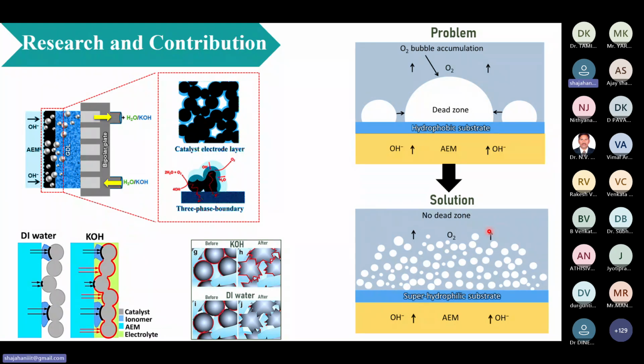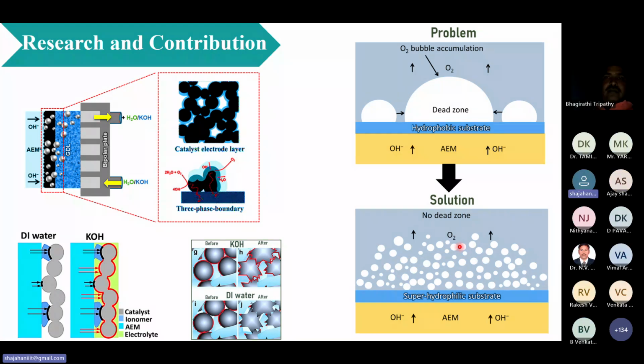Then how to do that? We have to prepare some superhydrophilic substrate or electrodes for the electrolyzer for the hydrogen evolution reaction on the cathode side and the oxygen evolution reaction on the anode side. For both, we can use the superhydrophilic substrate so that we can effectively remove the gases from the substrate without dead zone formation. So this topic is very interesting, because many people concentrate on the catalyst, but we concentrate on hydrophilic substrates.